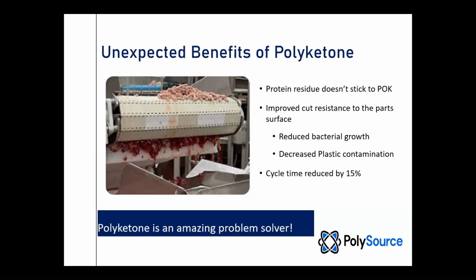Cut resistance was improved. They never had to replace a module because the cut marks were so severe that they were worried about bacteria. So we reduced that. And then, of course, because we didn't have any breakage with the polyketone, the concern for contamination was completely eliminated. And on the molding side of things, we were also able to reduce cycle time by 15%. So for the customer, polyketone was truly an amazing problem solver.